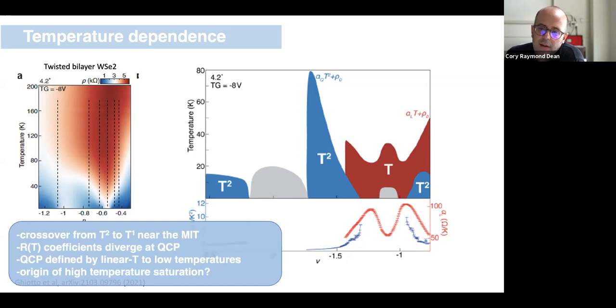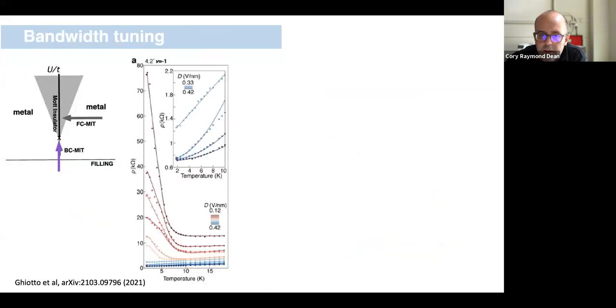Okay, so all this we believe is allowing us to identify a quantum critical point in the system. We observe that we have two quantum critical points, one on the overdoped side and one on the underdoped side. And we also note that away from that, we have this beautiful T-squared dependence, which identifies that there's a strong filling dependence in this system, which is a bit unique compared to similar discussions I didn't recap here about T-linear behavior that may or may not exist in the graphene bilayer systems. Okay, so one of the open questions is this high temperature saturation behavior, which again, I'm not going to discuss too much. So that's what happens if we tune by filling.